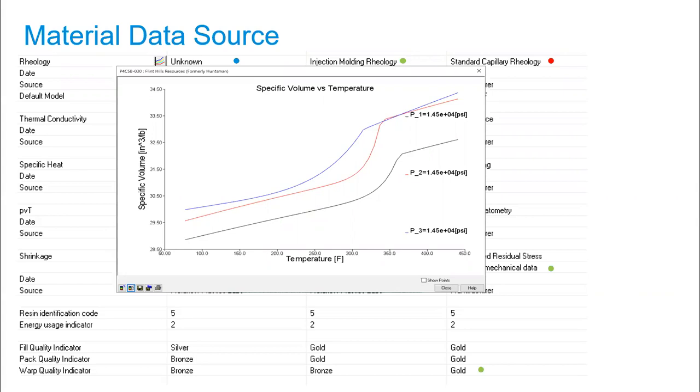And what's great about that is you can get close to what you're using in terms of your nominal wall thickness. You can look at your process and get an idea of an ideal situation of where your shrink is, parallel cross flow type of shrinkage, because we're doing these on tag dies, long rectangles essentially. So it doesn't necessarily get any easier than that. So if you're seeing shrinkages that are two, three times that in your model, you have a really good baseline to go to of what the ideal is and what to expect.